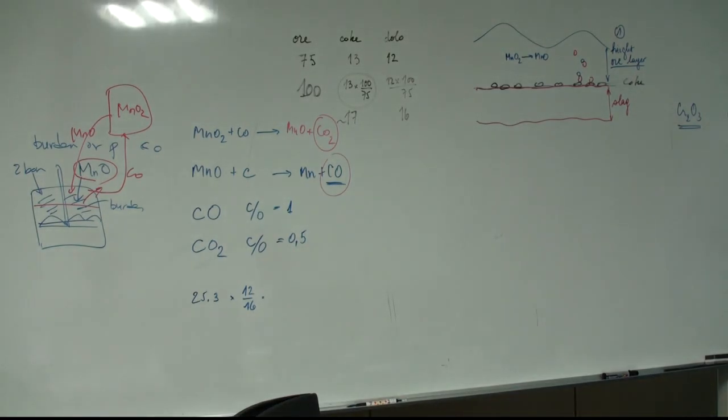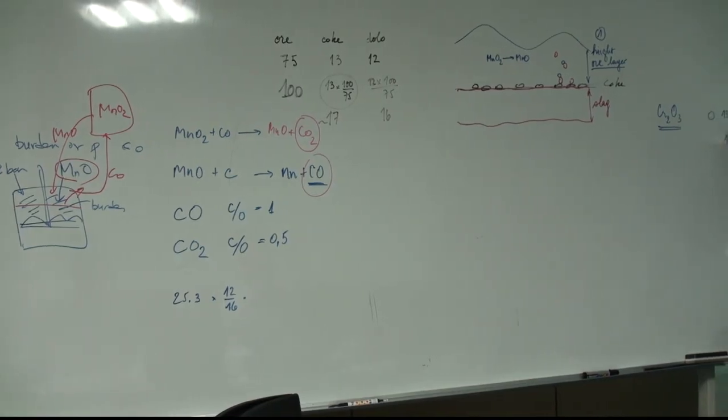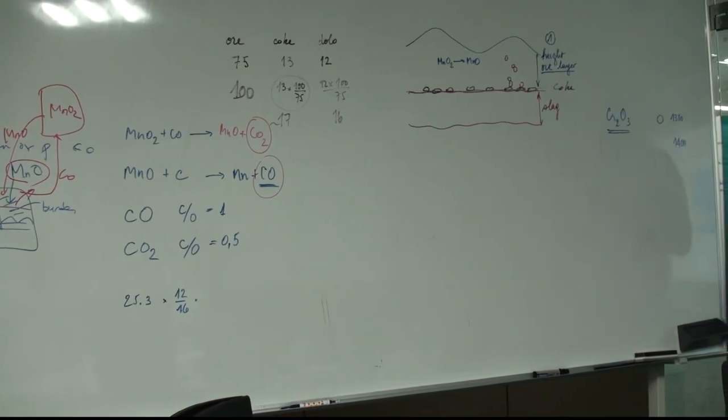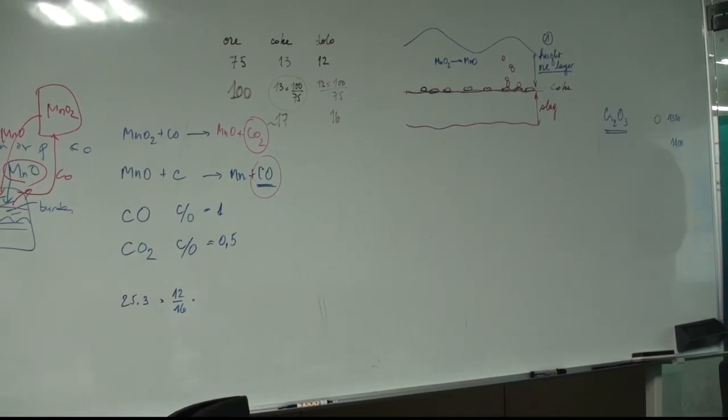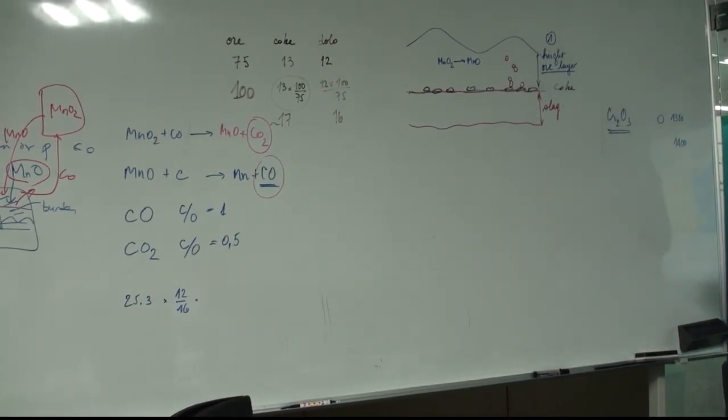We had no pre-reduction, and once we tested 1400, then we had pre-reduction, but it began also to melt. The result was exactly this.